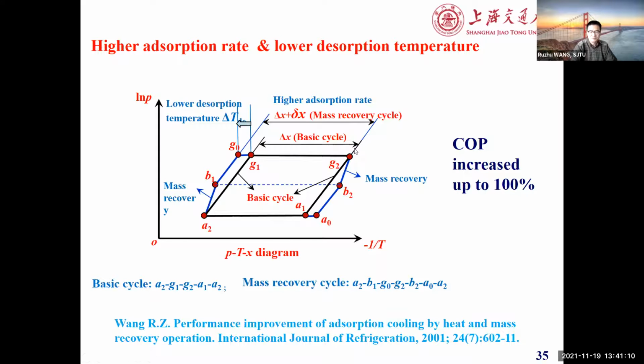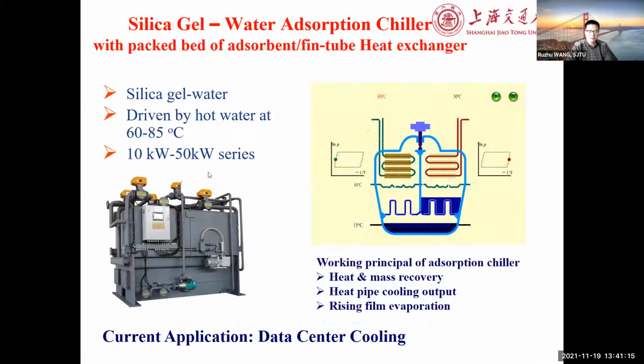So it's very simple. And then we developed this commercialized product from 10 kilowatt to 50 kilowatt. Adsorption chillers usually need about 60 to 85 degrees hot water to power. And this just shows this is the evaporator. Actually, that's an adsorber, condenser, receiver. But here is the evaporator. So when this adsorber is cooled down, you get the evaporation here. In this case, the cooling could be output to this thermosiphon. So you get 15 degrees in and you get 10 degrees out.